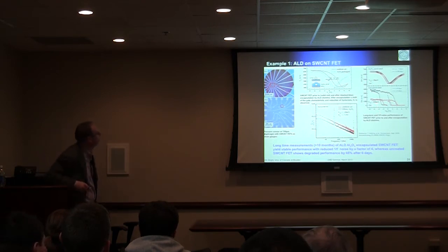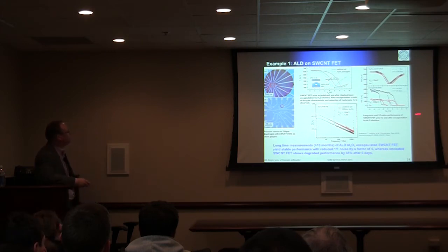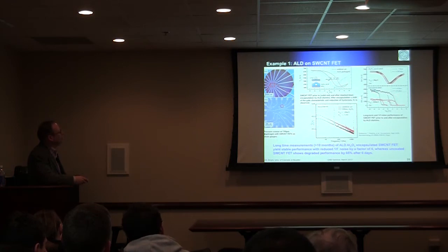curves, the black curve is what you see in here, the current versus voltage for this FET. This is 6 days. After 6 days, you can see how much shift you get. Okay, the device is totally unstable after a few days.